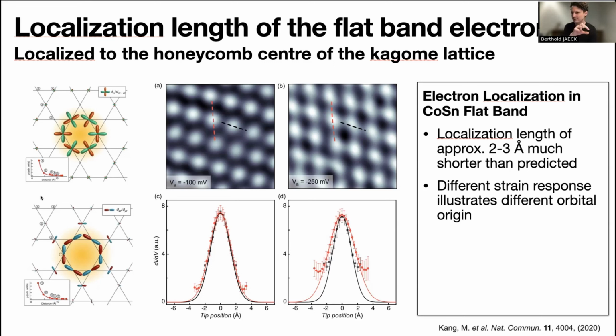We basically take a constant height, take constant current measurement and record the topography. We do this outside of the flat band near the dispersive states to essentially visualize the topography. Once we have that, we go back and replay the profile while we record the dI/dV amplitude at a given set point. So it's not exactly a constant height measurement. It's a corrugated topography that we follow while we map out the dI/dV amplitude. With this, we hope to be the least sensitive to any set point effects.